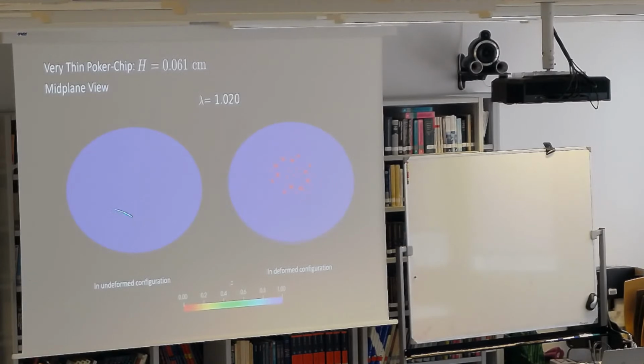So this is a picture of the midplane in the undeformed configuration, and this is in the deformed configuration. So we're in the context of finite deformations, right? Things look different in both configurations. So you can see that you have nucleation all over the place. You get many, many, right? This is what we saw in the experiment. And so this is what happens according to the theory. And it seems to be in agreement with experiments.